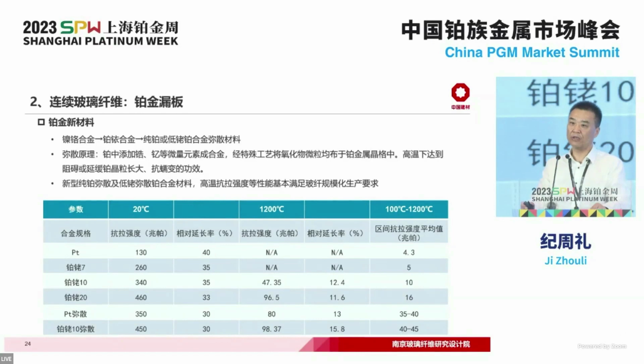And later, we wanted to try iridium, maybe using a platinum-iridium alloy to take the place of platinum and rhodium. In North China, in a cluster of crucibles, they tried this solution as well, but it didn't work either. It's because in ambient conditions, the platinum and iridium alloy is pretty similar to platinum and rhodium. But when the temperature is over 1,000 Celsius degrees, the iridium will vaporize, and the vaporization speed is 300 times that in ambient conditions.